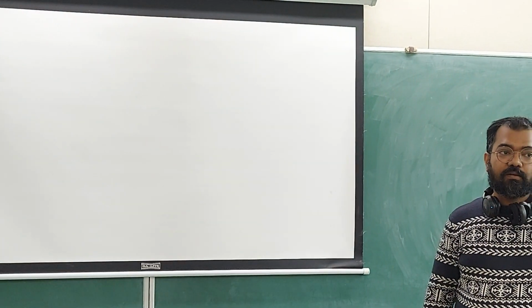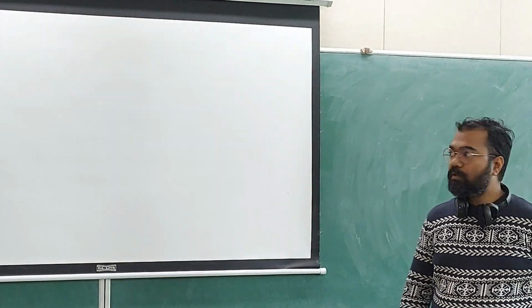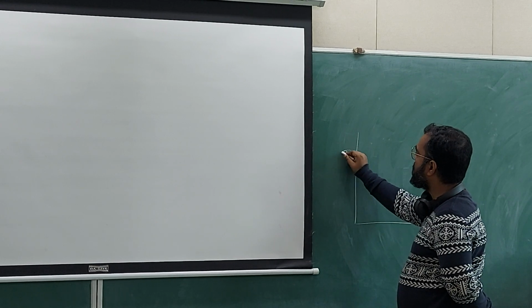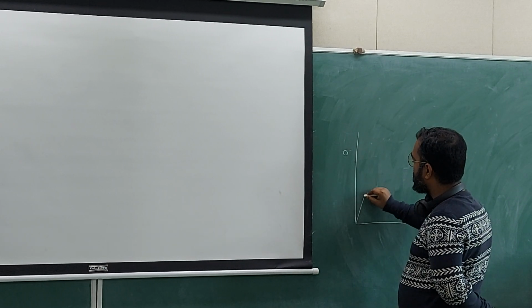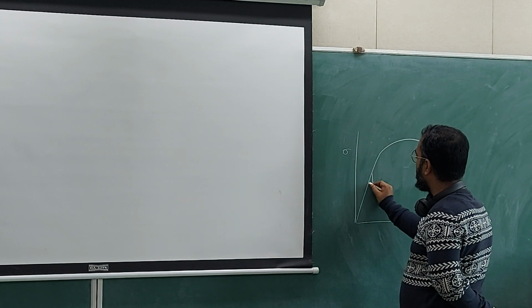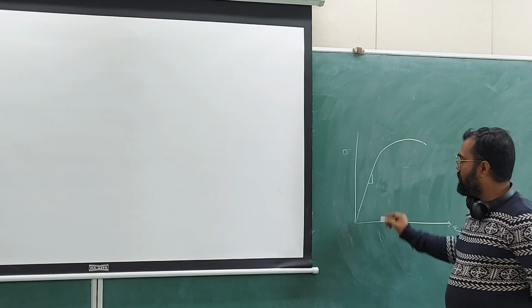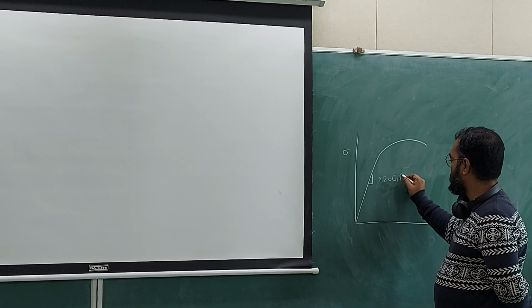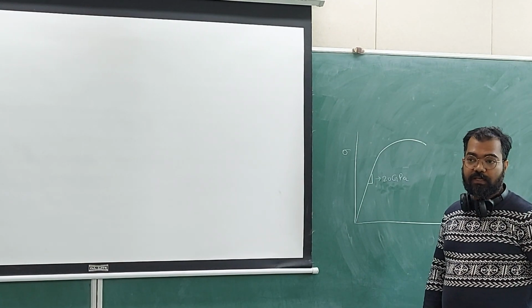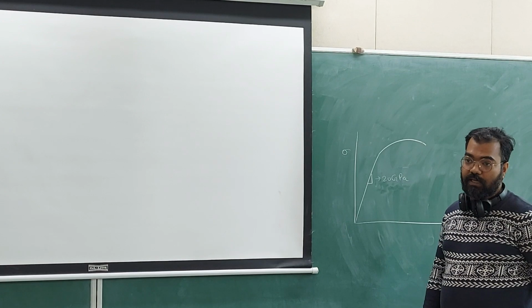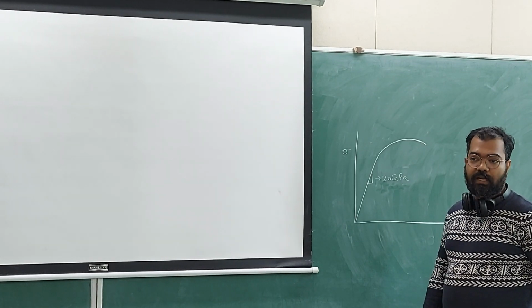Why? Why can you not measure Young's modulus from tensile test? It is not directly measured, but we calculate from the slope of the curve. Yeah, but that will be wrong. So if your steel sample has a Young's modulus of 200 gigapascal, then the slope which you will be calculating from your stress strain curve in a tensile test will only be somewhere around 20 gigapascal. So 10 to 20% of the real value you will get. Okay, you will never get 200. Why?